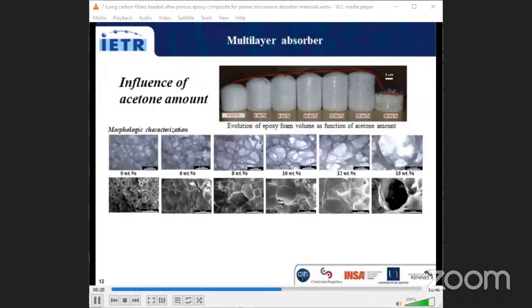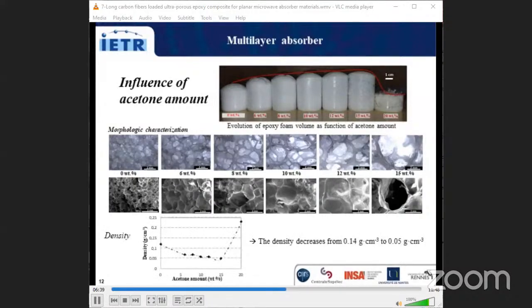The optical and SEM images show that the size of pores of epoxy foam increases when the amount of acetone increases. By varying acetone amount, we succeed to reduce the density from 0.14 for epoxy without acetone to 0.05 by using 15% of acetone. After this amount, the density increases because the foam structure is altered.